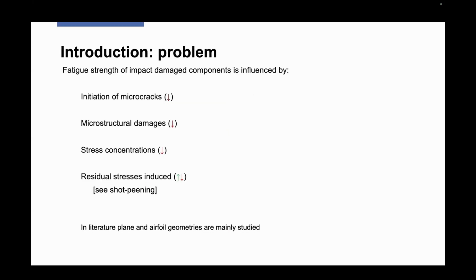So which are the mechanisms involved? We have the appearance of microcracks, of microstructural damages, and the appearance of stress concentrations that, as known, decrease the fatigue strength of components. But we have also the introduction of residual stresses that can improve or decrease the fatigue strength of the components, according if they are tensile or compressive. In case of compression, we have an improvement. In case of tensile stresses, we have a decrease. It is the same mechanism of shot peening, more or less.